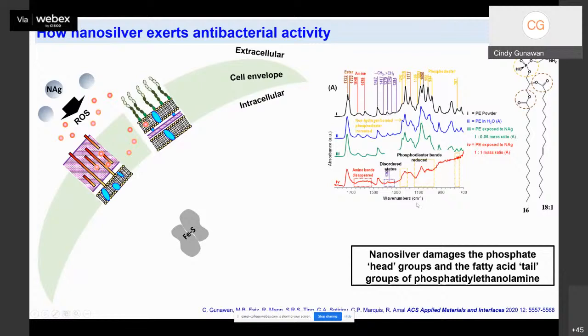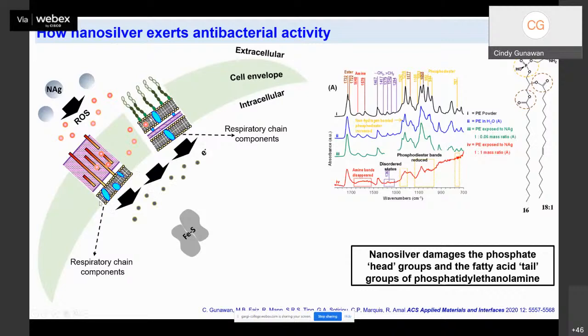With our infrared spectroscopy, we could see that the nanosilver damages the phosphate head groups of the phospholipids as well as the fatty acid tails of the phospholipids. So these damages caused by nanosilver on the cell envelope, in particular those on the phospholipids that compose the inner membrane, will disrupt the respiratory chain components that are embedded in the inner membrane of bacteria. And as a result, there will be a disruption of the electron transport chain from the respiratory chain components, such that we will have leakage of electrons into the cytoplasm.